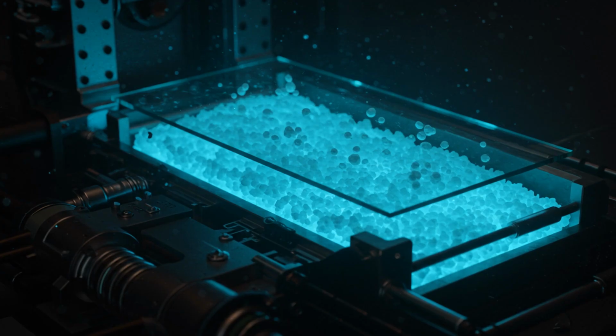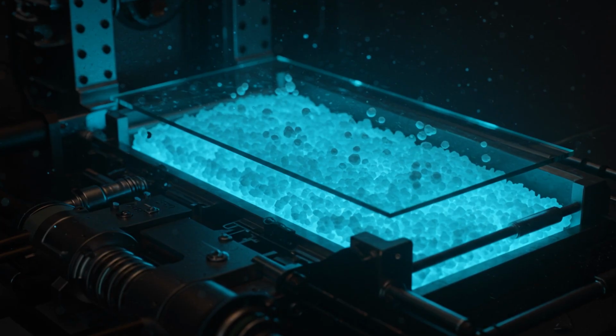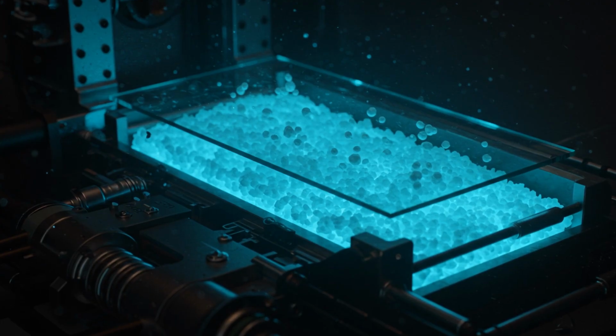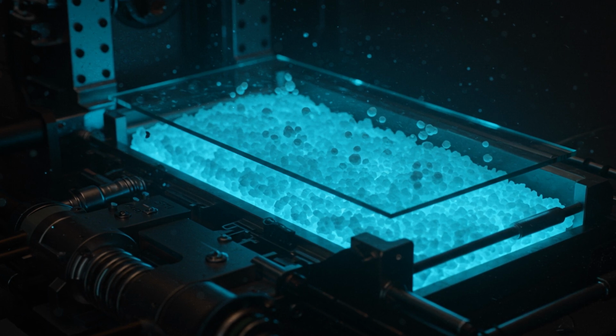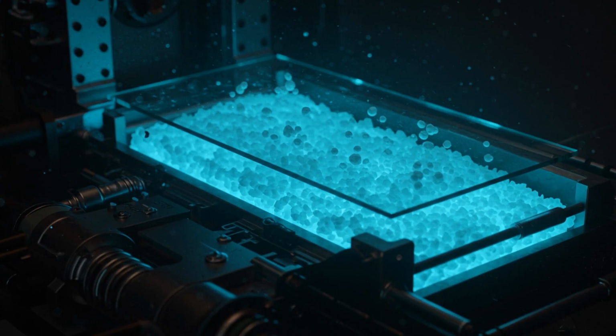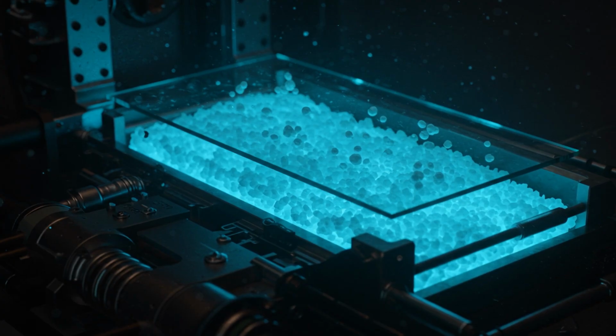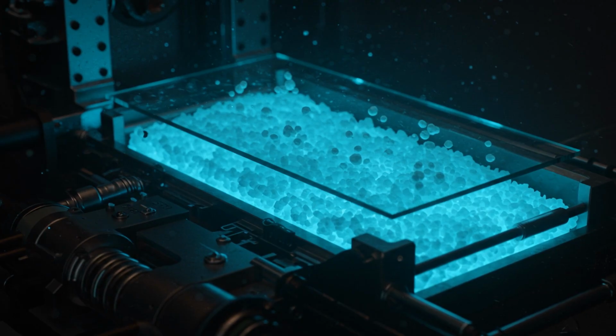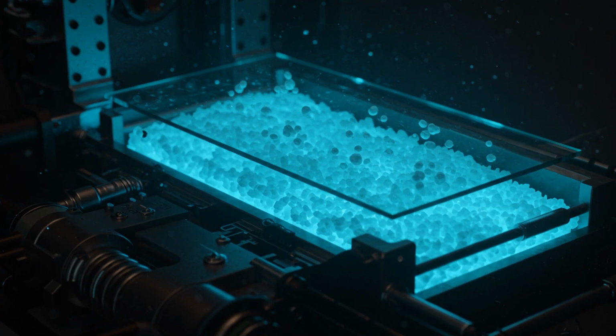Even at 30 micrometers, the glass is still too fragile. To make it tough, it must undergo a process called chemical strengthening through ion exchange. Imagine the surface of the glass as a crowded room. Currently, it's filled with small sodium ions. The glass is submerged in a pressurized, molten bath of potassium salt, heated to about 400 degrees Celsius. Through a process of diffusion, the smaller sodium ions leave the glass, and the larger potassium ions from the salt bath take their place. Because these potassium ions are much larger, they wedge themselves into the molecular gaps, creating a state of high compressive stress on the surface.